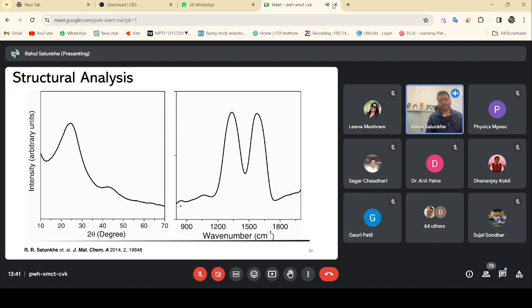If we see the structural analysis, there are mainly two peaks, associated with 002 and a very small peak here, and it represents a graphitic type of carbon, whereas Raman analysis shows D band and G band. If we consider ZIF-8 carbon, it is highly porous and amorphous, whereas ZIF-67, where the metal source is cobalt, leads to formation of a graphitic degree in the carbon. Because of that the surface area might be a little low, but the conductivity associated with this kind of polyhedra is very high because of the high graphitic degree.